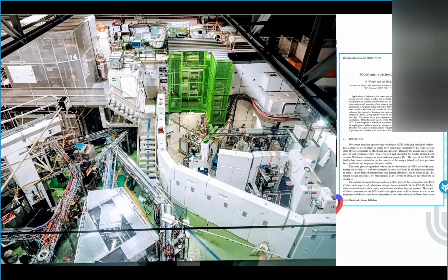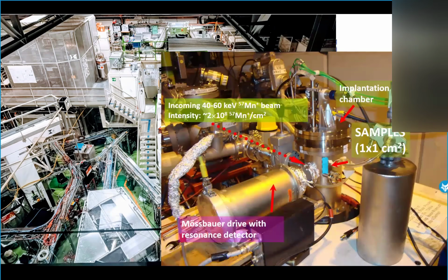Now, I'm here to say the good things, the bad things at the coffee. And this is a closer look at the setup. The setup at the end is a conversion electron Mössbauer setup. You have a drive, and here is the detector, and it's the detector that is moved in order to perform the spectroscopy. The sample is here in blue in your implantation chamber, and this is the beam of manganese-57 coming through. And then upon implantation, you record your data with the parallel plate avalanche counter placed in front.